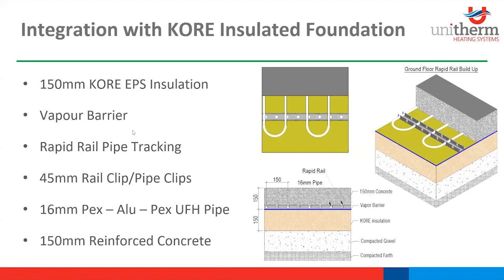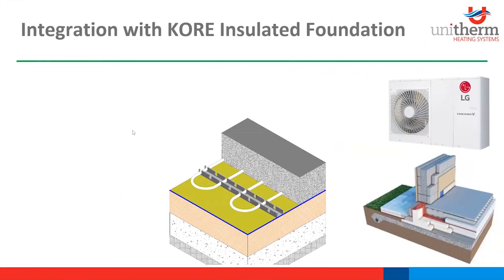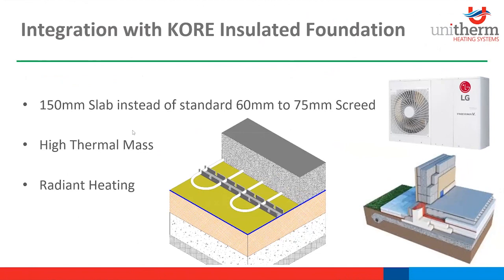So then we have 150 mil reinforced concrete, so the pipes are in that. Obviously we've twice the amount of heated screed or heated slab as we would normally have, compared to a 75 mil screed. So I'll just talk to you a bit further about that. As mentioned previously, for a 75 mil screed, the method of heat transfer from the heated floor is about 55% radiation and the other 45% convection. So with a 150 mil slab instead of a 75 mil slab, we've now doubled the thermal mass in the floor, therefore significantly increasing the longevity of radiation from the floor. Because the majority of the heat is now predominantly radiant, it creates occupant thermal comfort at even lower air temperatures.